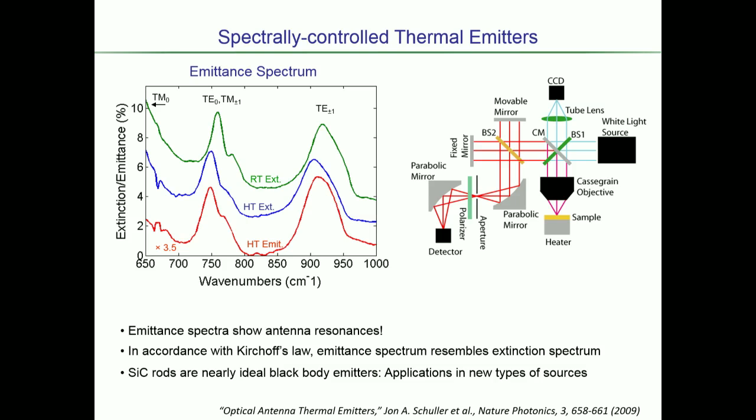So the key point to take away here is that if I take an extinction spectrum here in the blue, at the region where silicon carbide shows these strong high epsilon, and the whiskers themselves show me resonances, I can actually see these peaks, and these peaks can nicely be identified with the Mie resonances of the silicon carbide whisker.